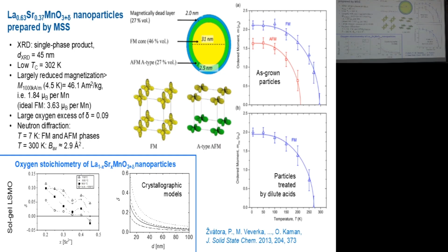And this somehow altered the magnetic properties and the fundamental properties of these particles, because this perovskite phase has a very, very complicated magnetic phase diagram depending on the ratio of lanthanum and strontium, depending on the ratio of manganese 3+ and manganese 4+. It's fascinating. It's very rich and complex. And by this synthesis, we shifted the particles from the nominal composition with a certain ratio of manganese 3+ and manganese 4+ to a region of higher oxidation, and these particles behaved like containing more strontium 2+ than they actually contain.